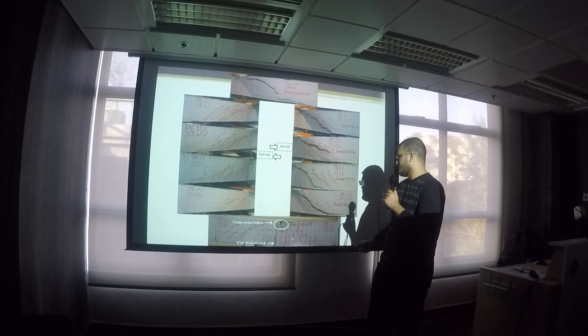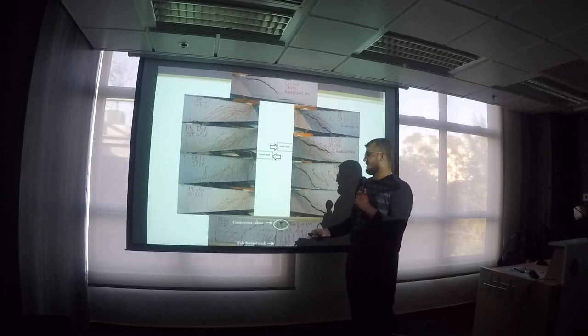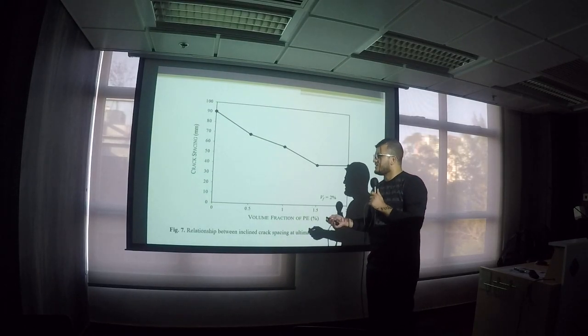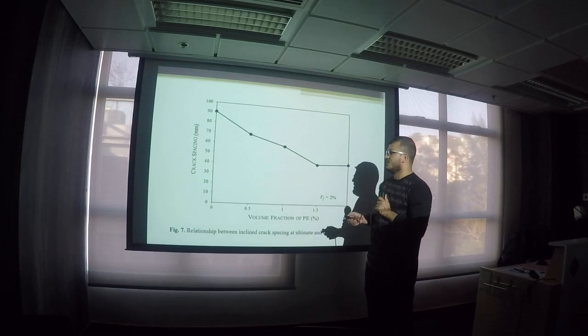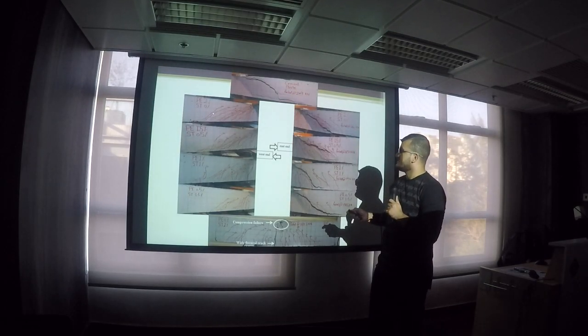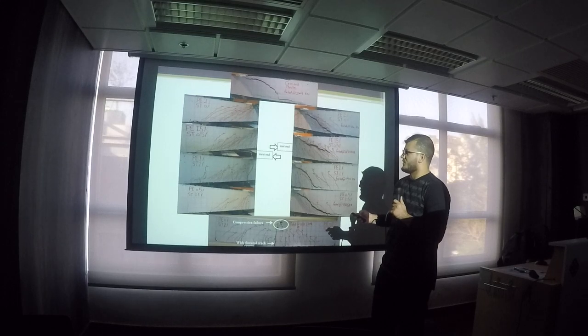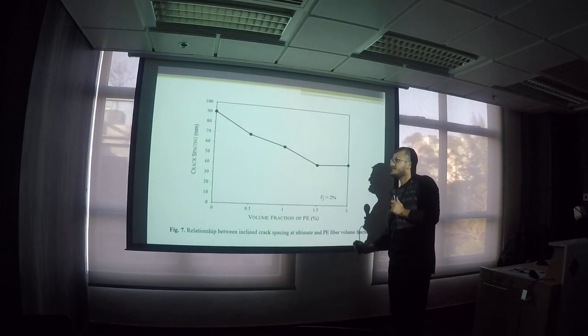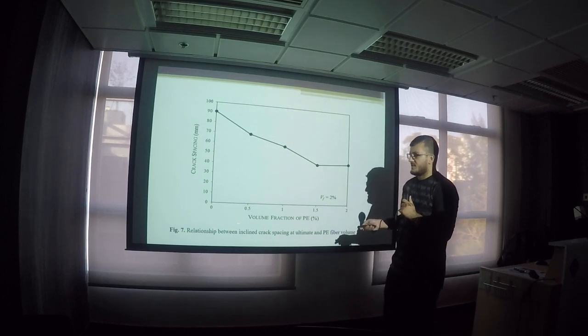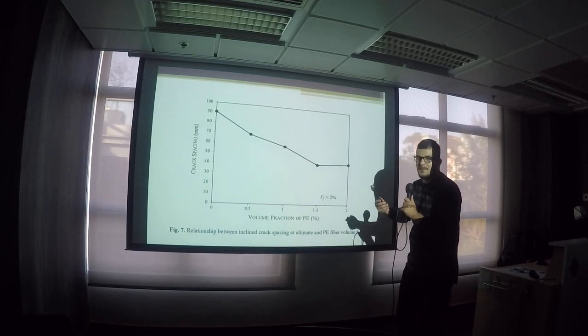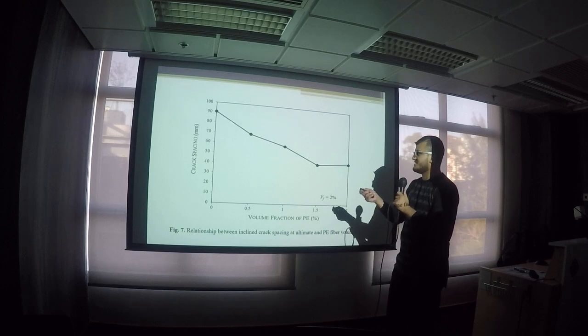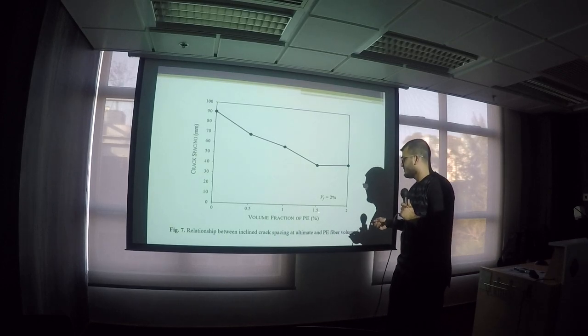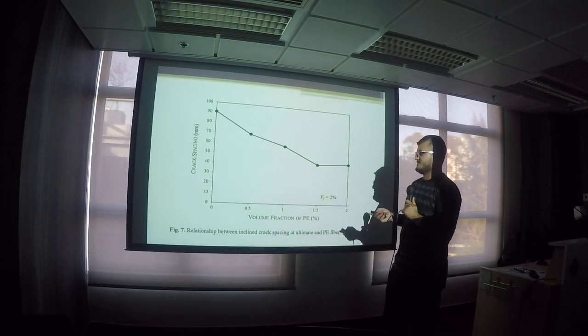And as I say here, this one has 2% steel. This one had the highest strength and it failed in flexure, not in shear. But if you compare the shear cracking, here we have lower shear cracking than here because the polyethylene volume here is approximately 0. So we got the relationship between the crack spacing and the hybridization ratio. The crack spacing was calculated by dividing the distance between the cracks over the number of cracks minus 1. And we have got this relationship. So as I say, increasing the polyethylene volume fraction leads to extra multiple cracking behavior, which means that the crack spacing will be lower and lower. So increasing polyethylene volume leads to a decrease in the crack spacing.